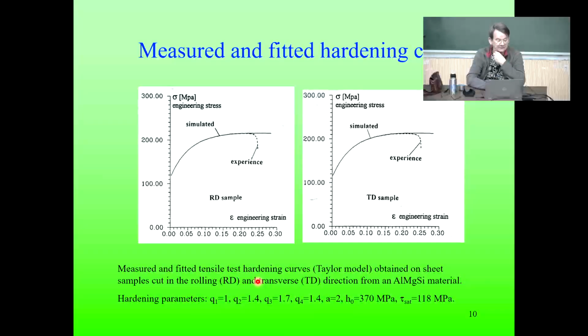Here is a demonstration. This is a real tensile test of aluminum, magnesium, silicon material in the RD and then TD direction. And you can see that if one follows the procedure, polycrystal plasticity is reproducing the macroscopic observations fully, perfectly. Of course, there are parameters in it. There are a number of parameters. Here they are. But the result is quite spectacular.